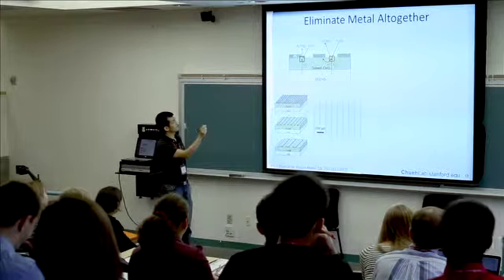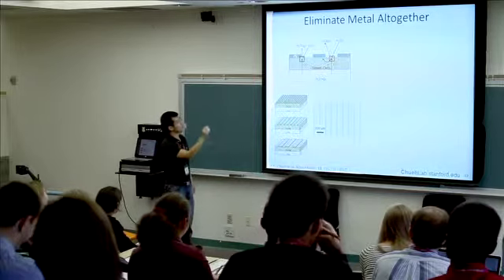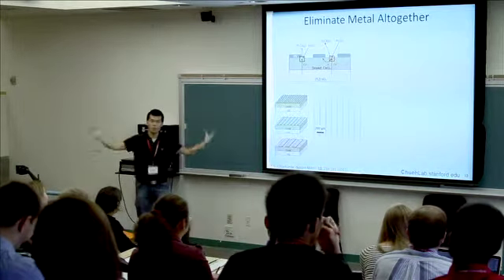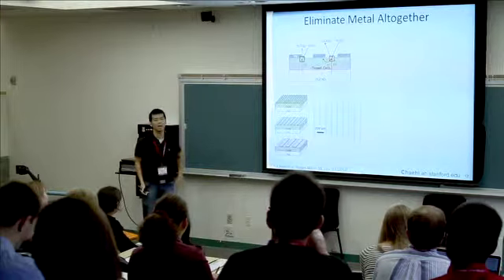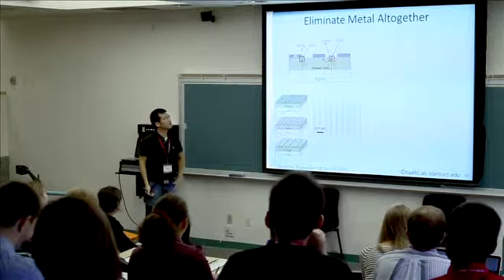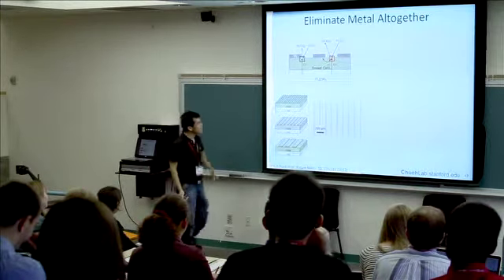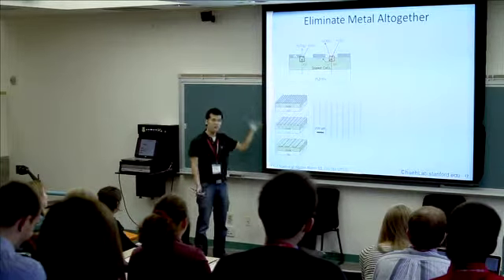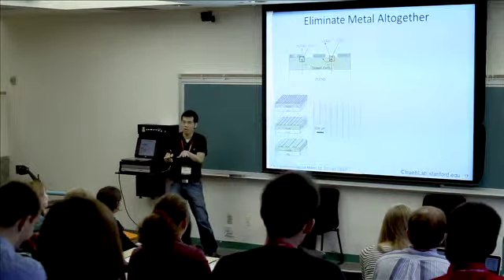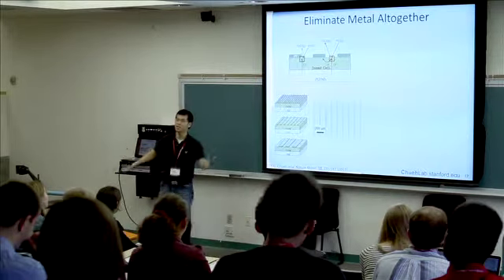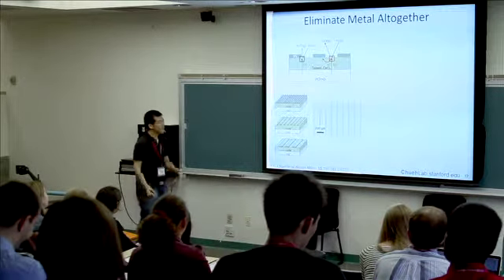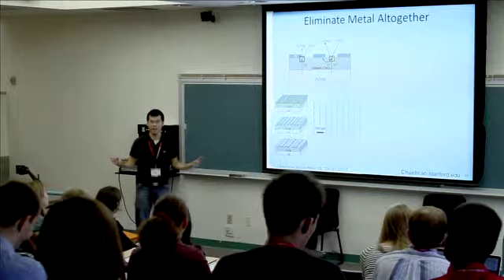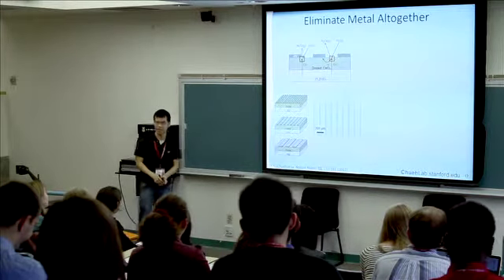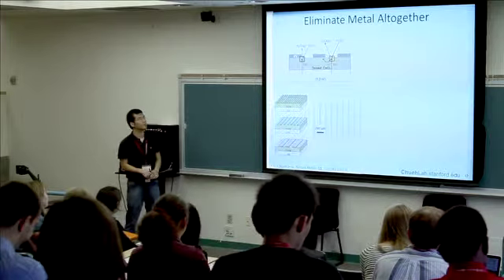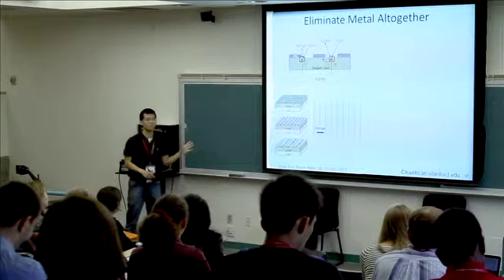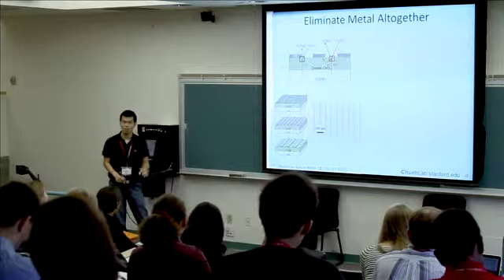Okay? So you have a surface like this. You have platinum features on cerium oxide, which is a catalyst, and you have hydrogen and water in the gas right above the cell. What is very strange is that when we change the amount of platinum on the surface, so we made very, very small platinum or very, very large platinum, essentially changing the available reaction sites, we saw that there was no change in the activity of cerium oxide as a catalyst. So we immediately confirmed that platinum was much worse than cerium oxide when it comes to high temperature catalysis.